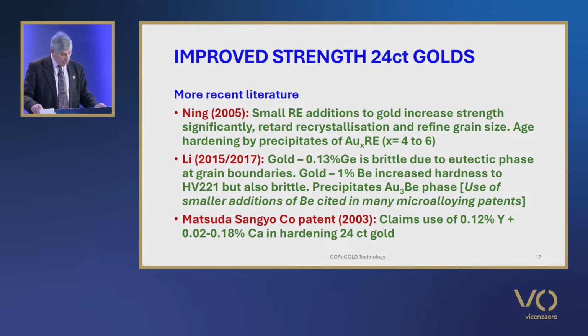In a study of a gold 0.13% germanium alloy, Li characterised the cause of brittleness that he found. The gold germanium phase diagram is a eutectic system. He found that germanium tends to segregate to grain boundaries as a eutectic phase, which led to the brittleness.